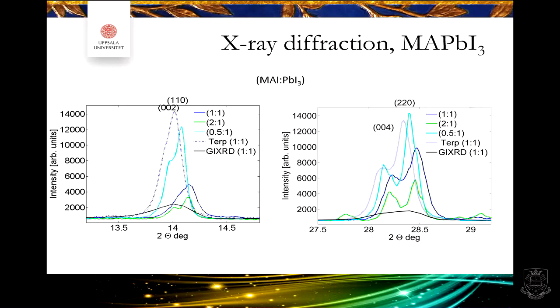So this is from powder XRD instead. So after you have seen the powders in the SEM, then you get a higher resolution and you can actually see these double peaks forming. But even if you have this double peak, so if you have a double peak, that means tetragonal phase, single peak, cubic phase. But I could also see that it varied between cubic and tetragonal phase. So here 1-to-1 is equal amounts. You have a stoichiometric film, but 2-to-1 is more MAI, and here we have more lead iodide instead.